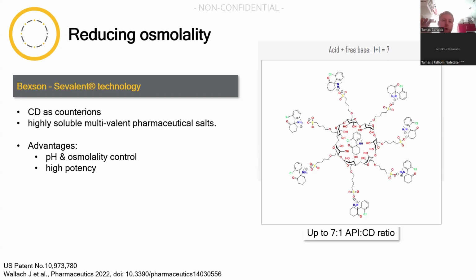The problem was with this particular cyclodextrin, the sulfobutyl ether beta cyclodextrin, which is a polyanion, as you can see here. These sulfobutyl groups with the sodium counter ion. So 10% of this cyclodextrin was already isosmotic.